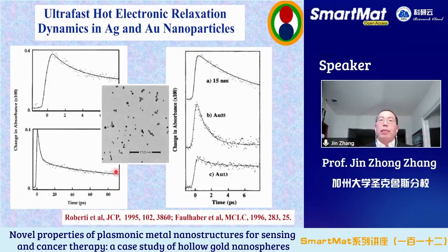That's similar to what Fujimoto observed at MIT on films of silver. So in some ways, they're not that interesting, because that means the particles behave similarly to a bulk material. At about 15 nanometers, they're still like a bulk. But when you make them 55 atoms or 13 atoms, these samples were made by Günter Schmid in Germany, who is a cluster chemist, and we were fortunate to collaborate with him, you can see the lifetimes are very different. The point is, once they become very small, between 55 and 13 atoms, they are more like a molecule. But once they are larger than 10 nanometers, they are like a bulk material. That was the conclusion then.